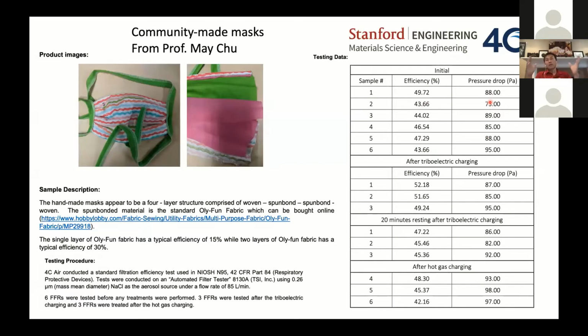If I compare with N95 masks, N95 typically has a pressure drop, for a very good brand, below 100 Pa. Some brands can go up to 120 Pa pressure drop. So below 100 is pretty good already for a community mask. And filtration efficiency is about 40%. If you look at surgical masks available to doctors, the requirement is typically above 30%. Some of them can go up to 40, 50, 70, 80%. There's a big variety. But this is already above the minimum requirement of a surgical mask in terms of sodium chloride filtration efficiency. So these are pretty good community-made facial masks.